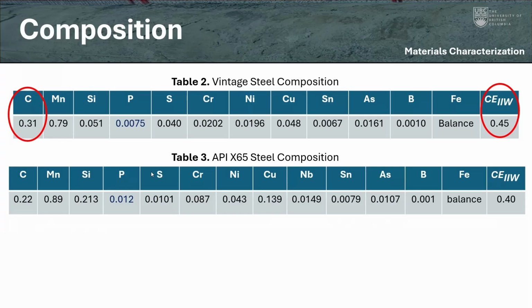And I specifically want to comment on the high carbon content we see, 0.31% compared to 0.22% of carbon. And also looking at the carbon equivalent. So what this tells us is that back then, manufacturers would rely on tuning the carbon content for increasing the strength or hardenability of that pipe instead of utilizing more recent alloying additions like niobium, titanium, or vanadium to also tune the mechanical properties.